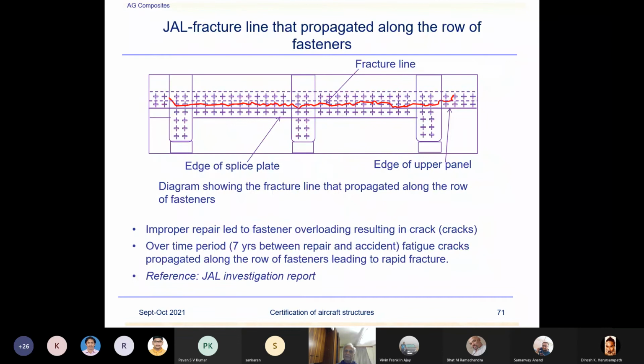You see this slide where the cracks initiated. Some cracks would initiate and then continuously they kept on growing. So improper repair led to fastener overloading, resulting in cracks. Over the 7 years between the repair and the accident, fatigue cracks propagated along the row of fasteners, leading to rapid fracture. So essentially, this is like widespread fatigue damage that gradually propagated and led to the failure.